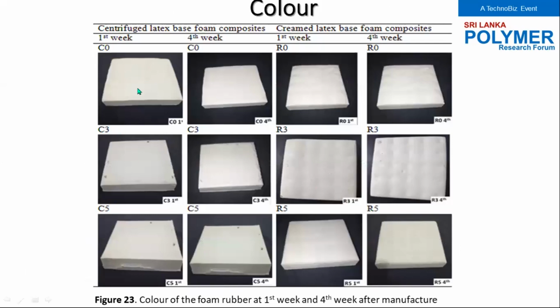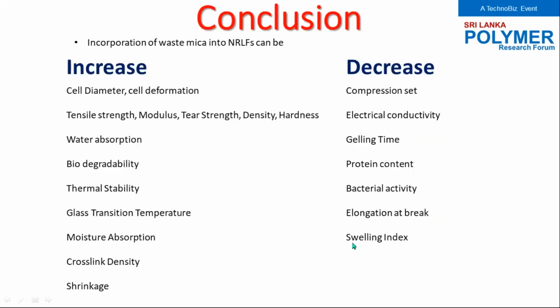I have observed the color changes of natural rubber latex foams with the time duration. However, there is no considerable color change with time. So in the conclusion part, I would like to separately introduce the increasing patterns and decreasing patterns. Cell diameter, cell deformation, tensile and mechanical parameters, water absorption, biodegradability, thermal stability, glass transition temperature, moisture absorption, cross-link density, and shrinkage-like parameters have increased. However, other parameters have decreased.